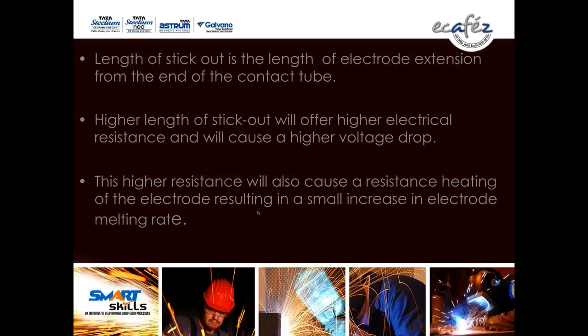Next, length of stick out. Length of stick out is the length of electrode extension from the contact tip to the tip of the weld. The length is called stick out or electrode extension. A higher length of stick out will offer higher electrical resistance and cause a higher voltage drop. The higher resistance will also cause resistance heating on the electrode, resulting in a small increase in the electrode melting rate.